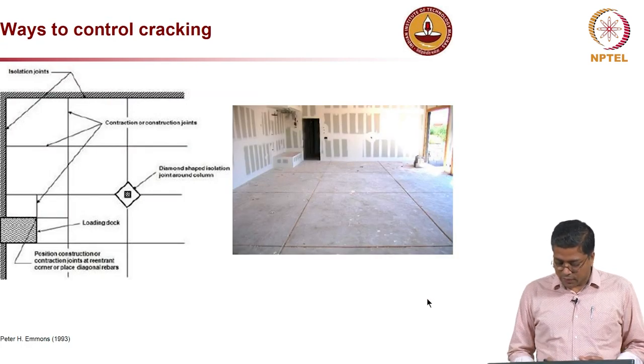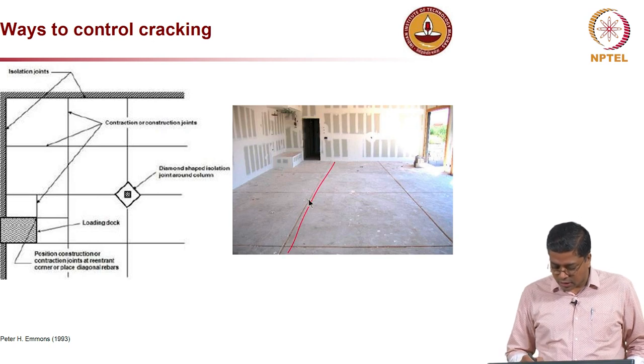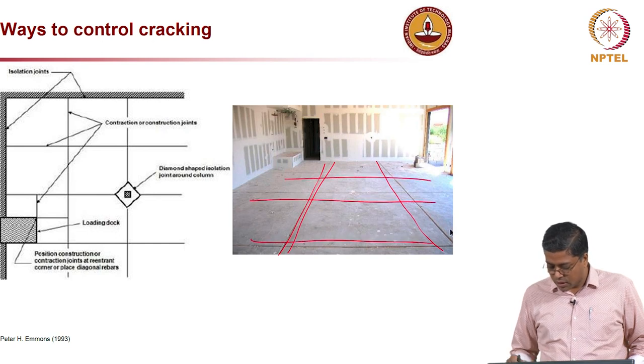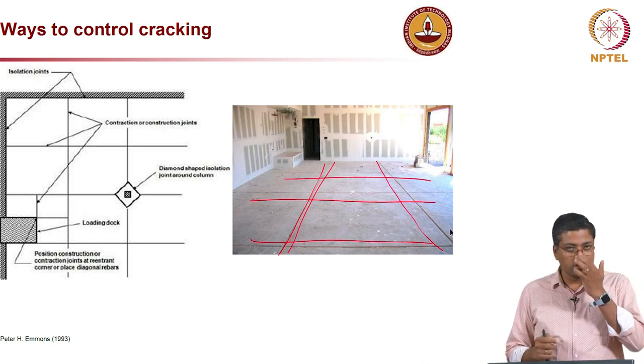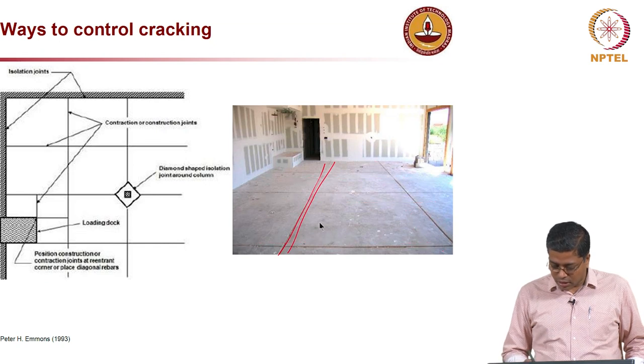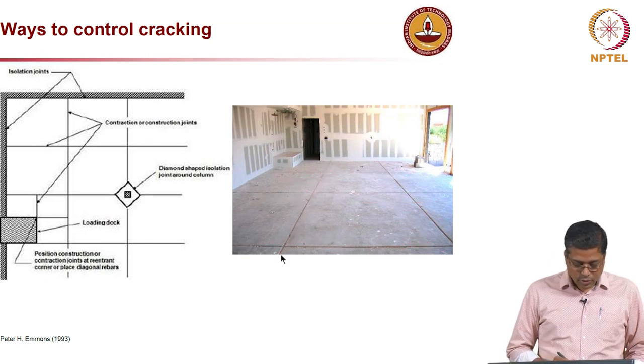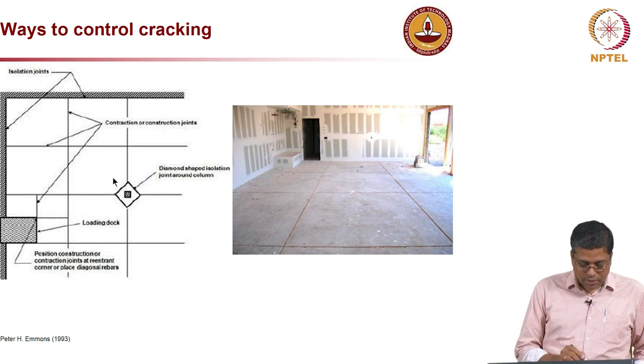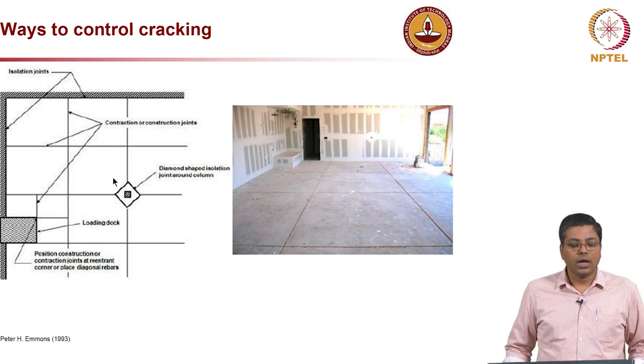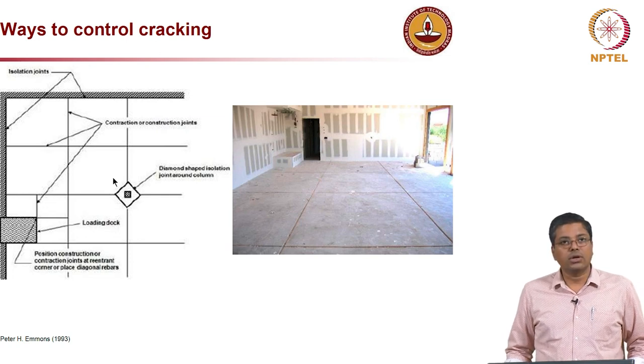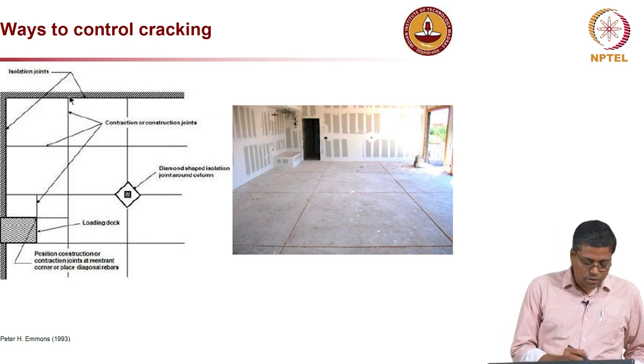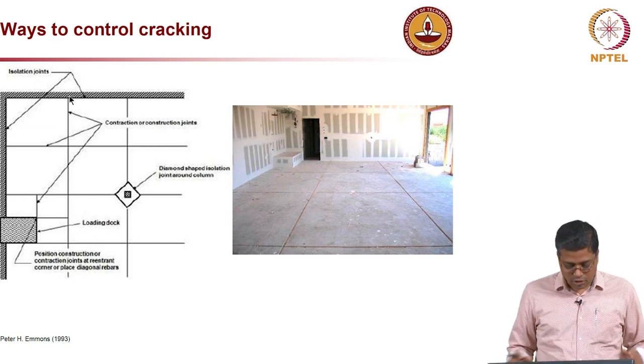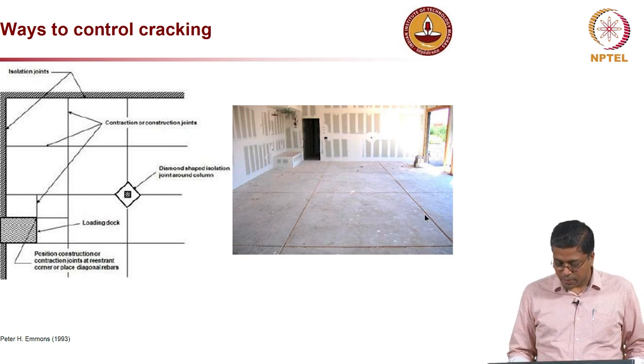Now this is for an interior structure. You can see here a large slab with saw cuts made like this, which will ensure that the crack is right below those saw cuts and is not forming randomly on the concrete surface. This sketch also shows a similar thing, a typical plan on how we can make contraction or construction joints and force the crack to happen right below such joints or saw cuts.